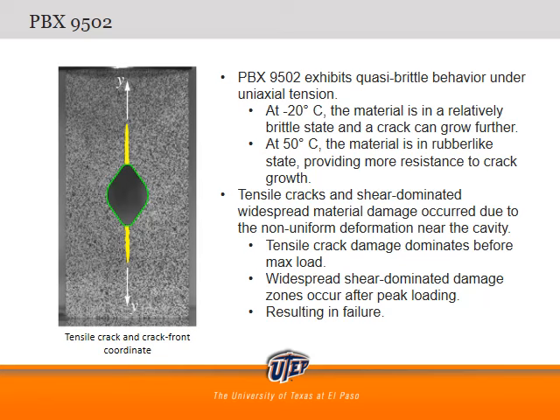Due to the presence of the cavity as well as the shape, tensile crack and shear dominated widespread damage did occur to the material, as well as non-uniform deformation near the cavity, which was the cause of these failures. As you can see in the graph in the previous slide, tensile crack damage dominates before the max load, and then widespread shear dominated damage occurs after the peak load. This causes the load to go down because the material can no longer support it, resulting in failure.